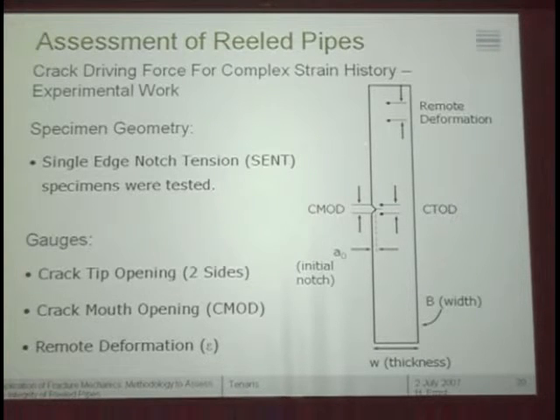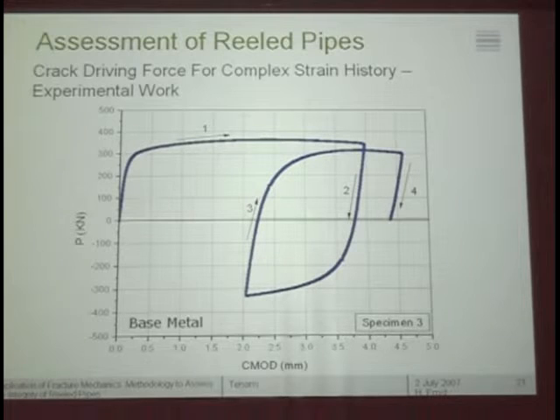So this is the same specimen. We measure there the CMOD, we measure a CTOD that is very close to delta 5 because we actually measure the distance between 2 points from both sides, and of course we also measure the remote deformation. And this is just an example. This is a load CMOD curve. We went all the way to 1. We did have a little bit of crack extension here, but we continue on to 2, 3, and then 4. So this is about 2